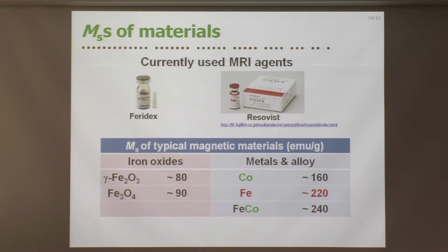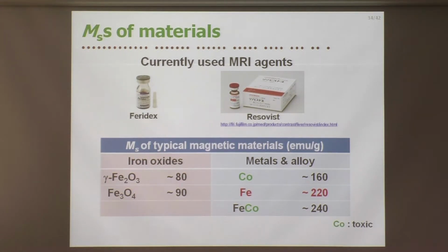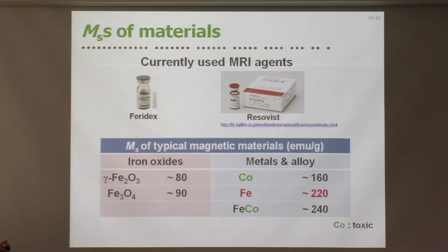As explained, a certain composition of iron-cobalt alloy has very high, the largest, saturation magnetization. So this material seems good for biomedical applications. However, cobalt is known to be toxic to humans, so we cannot use such materials.